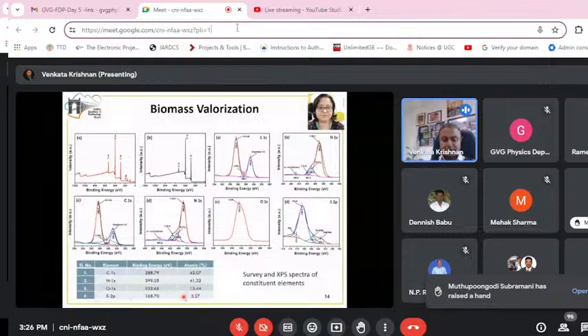Since sulfur is present on the surface, we were able to understand that sulfur is present at 3.27 atomic percentage on the surface of the sample.